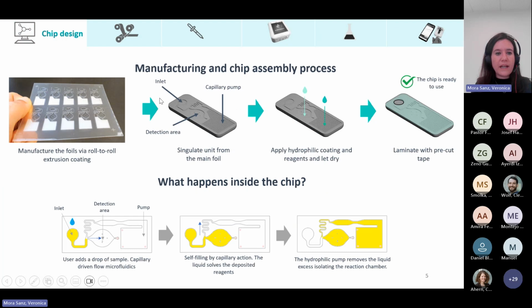So here we can see a foil with several units of the chips produced by roll-to-roll extrusion coating. Here we can see a single unit of the chip that is composed of an inlet, a detection area, and also a capillary pump. We have to introduce the enzymatic substrate here in the reaction chamber on the chip, and apply a hydrophilic reagent in the capillary pump. And then we have to close this chip, and for this we use a pressure sensitive adhesive tape. We close the chip, and then it is ready to be used.